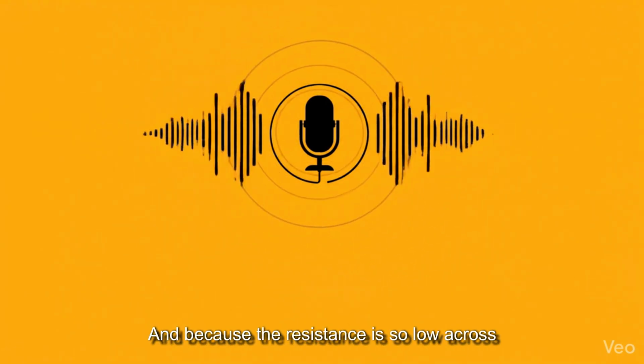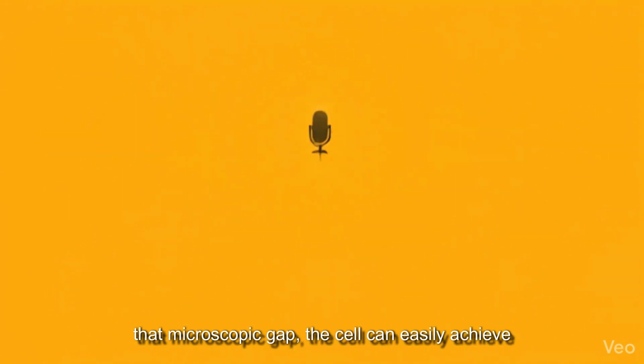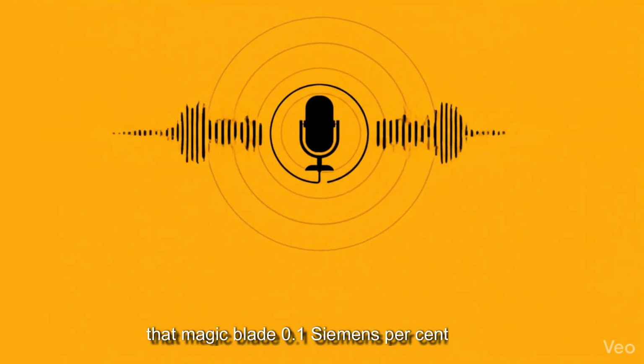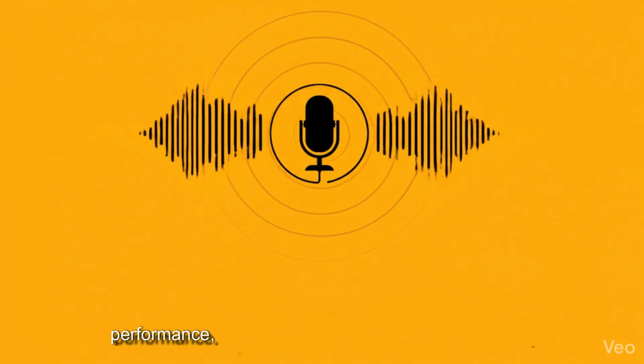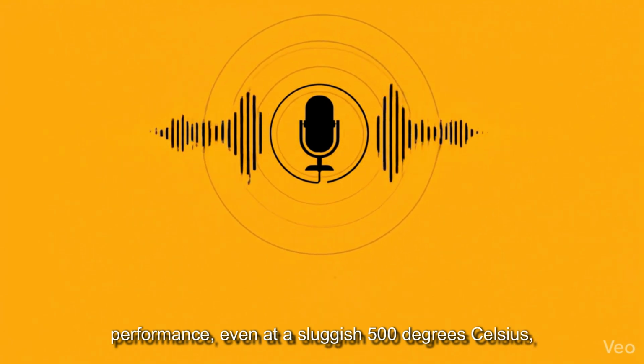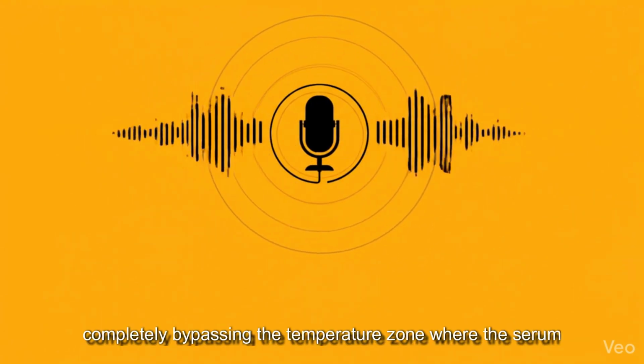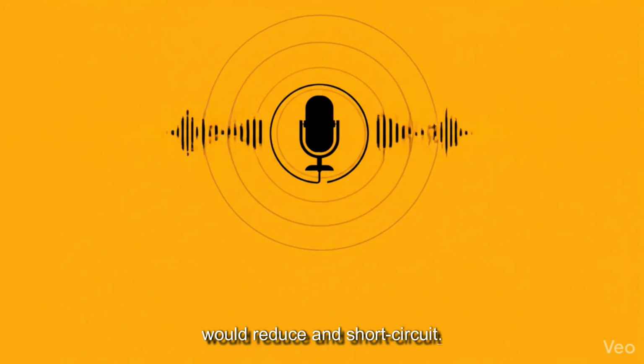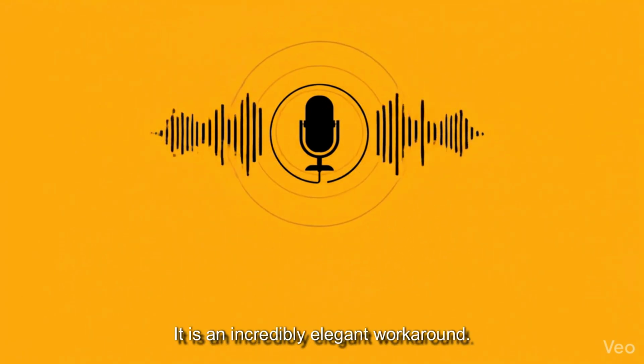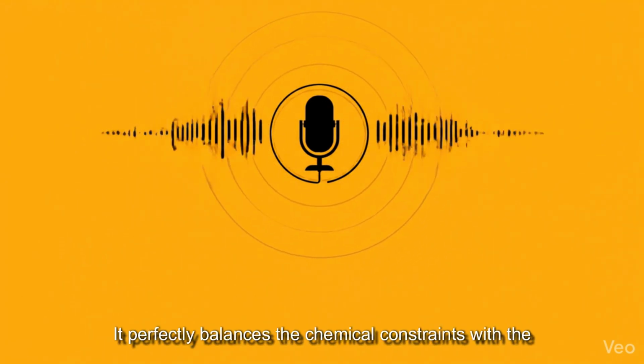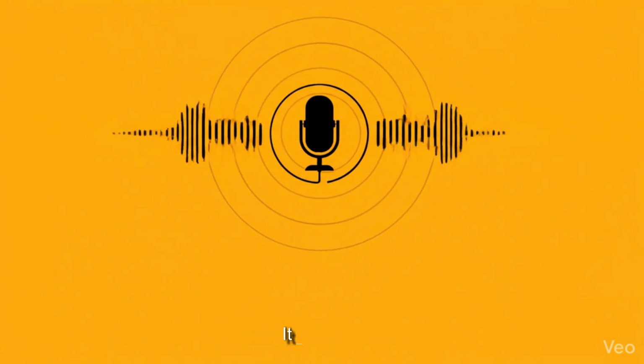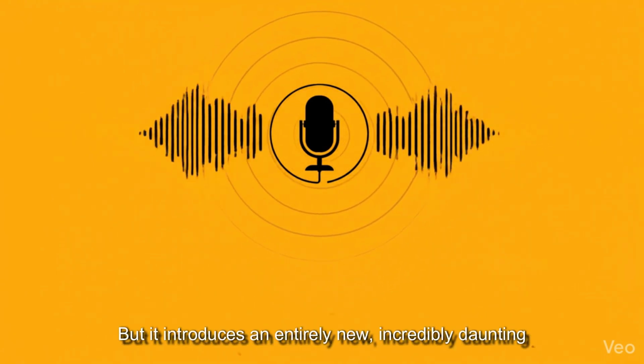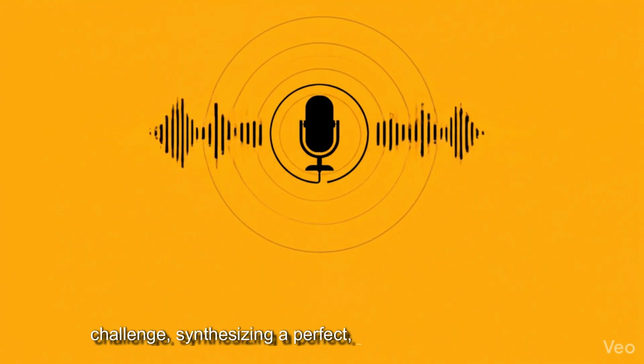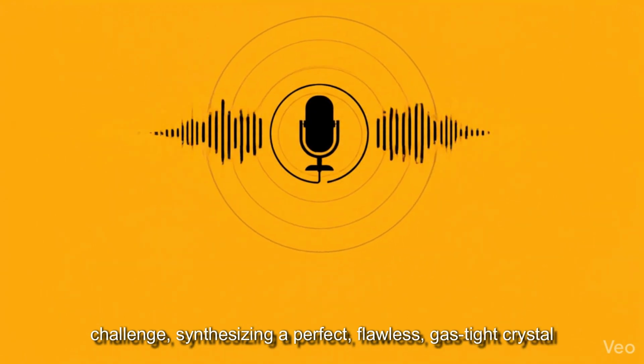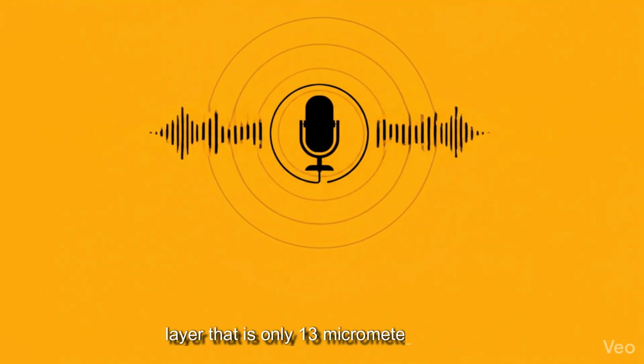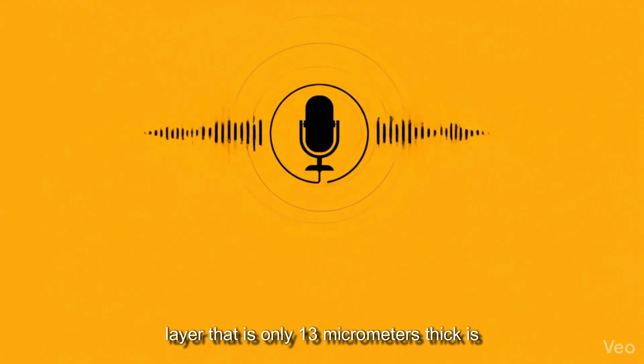And because the resistance is so low across that microscopic gap, the cell can easily achieve that magic 0.1 Siemens per centimeter performance, even at a sluggish 500 degrees Celsius, completely bypassing the temperature zone where the cerium would reduce and short circuit. It is an incredibly elegant workaround. It perfectly balances the chemical constraints with the electrical requirements. It really is. But it introduces an entirely new, incredibly daunting challenge. Synthesizing a perfect, flawless, gas-tight crystal layer that is only 13 micrometers thick is exceptionally difficult.